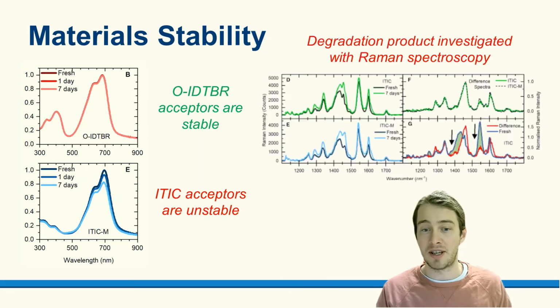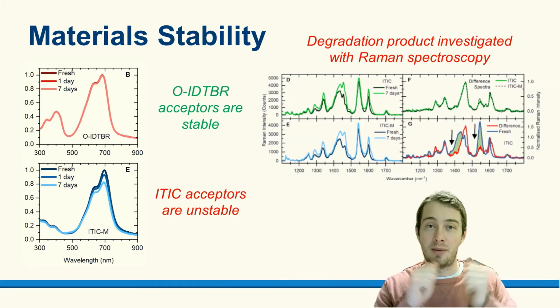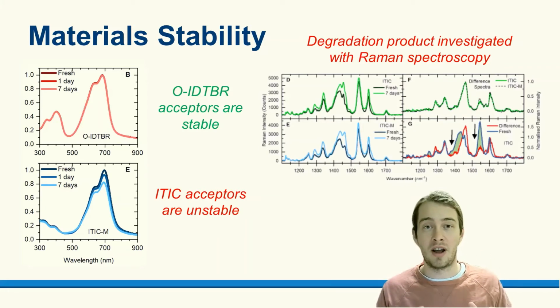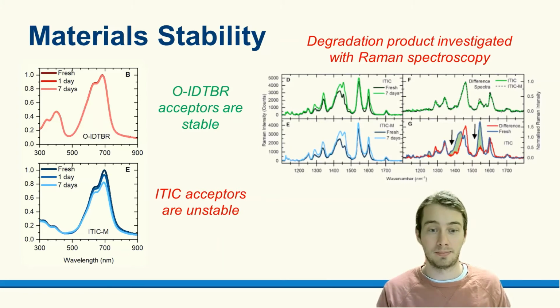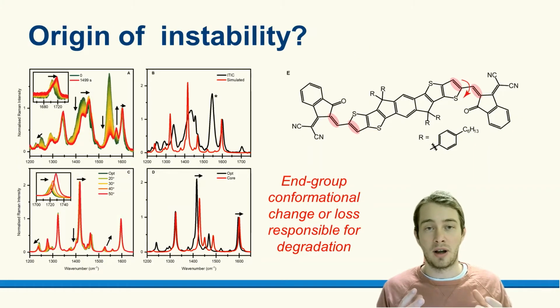And to characterize this in a bit more detail, we use Raman spectroscopy, which is a vibrational spectroscopy that's sensitive to the vibrations in a molecule between the atoms, and we can learn about the structure of our degradation product. So now we've got our Raman spectra of our degradation product. We wanted to see what the origin of this degradation product is. And so we did some simulations, and you can simulate the Raman spectra of the molecule with different degradation products. And what we find is that our experimental spectra suggests that there is some kind of conformational change or even loss of the end groups of the ITIC, which you can see highlighted in the molecule above.